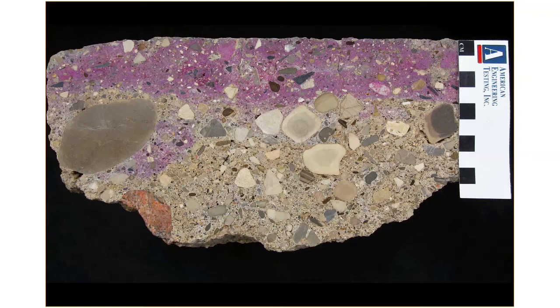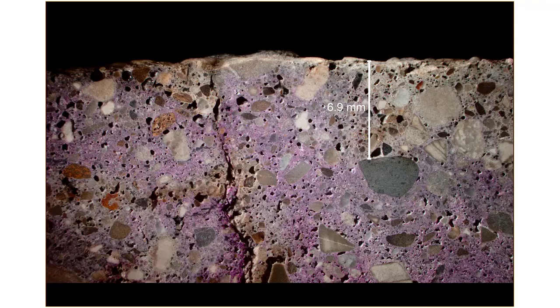Next slide here, as we get a little closer in magnification, we're actually under magnification, and we're using low angle light. Low angle light casts some shadows. First thing, we've got a 6.9 millimeter depth of carbonation. It's ranging from negligible just to the left there, and spikes upwards of 7 millimeters along cracking. You can see a crack with carbonation intermittent down along it. Just a little farther to the left, you can see that crack progressing vertically down through the concrete. We can see some areas that are carbonated.